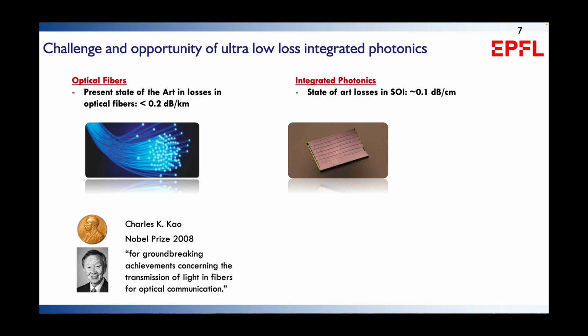That has been a challenge that over the last, say, decade, has really been addressed. And if you look at what can be done today in optical fibers, I'd say it's truly remarkable. Optical fibers have losses of 0.2 dB per kilometer, whereas integrated photonics in silicon is about 0.1 dB per centimeter. So there's a 5 orders of magnitude gap between the two.